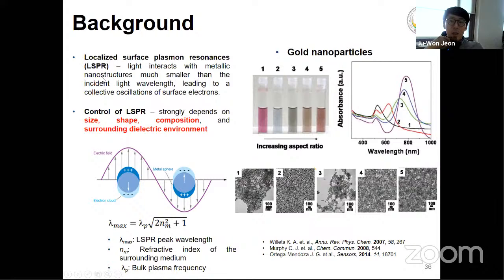And this LSPR property strongly depends on the metal size, metal shape, and composition of the metal, and also the surrounding dielectric environment. So below is the equation that relates the LSPR peak position, peak wavelength, and refractive index of the surrounding medium. And this is an example of gold nanoparticles. If the gold nanoparticle is a sphere, its color is pink, and the LSPR peak appears around 530 nanometer.